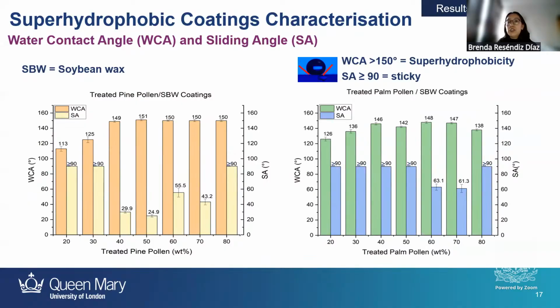So here is when I use soybean wax. I also want to observe how, depending on the wax that I'm using, the properties of my coatings change. For pine pollen soybean wax combinations, I can observe that from 80 to 50 I achieved 150, but the sliding angles were a little bit higher. This means that maybe the crystallinity of the wax could also affect it, but it might also be the morphology of the pollen that influences the contact angle.